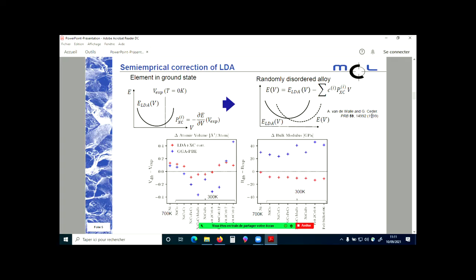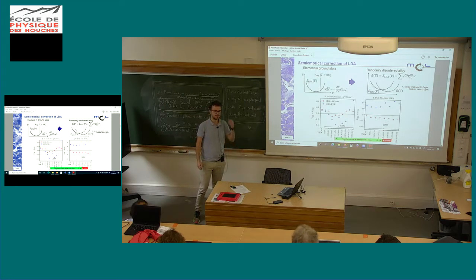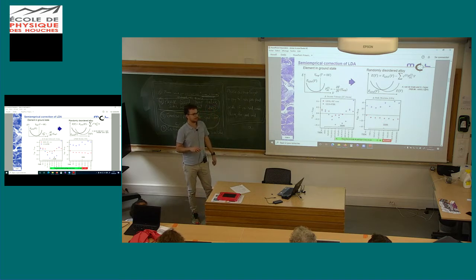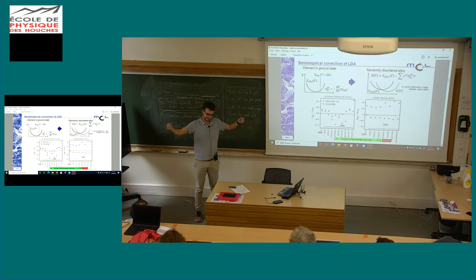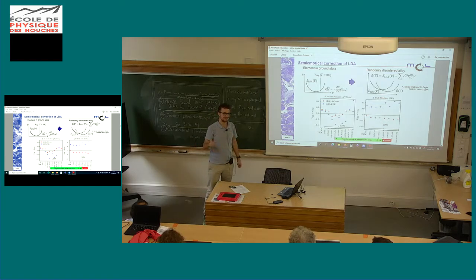Right. So, the point is, as you said, you actually almost need to use LDA to correctly reproduce the magnetic state. But somehow it's an effect that is only taken into account a posteriori. That means you basically just push your result to a place where it then really predicts correct lattice constants. So that's exactly the point of it. You just add a pressure, and you can even argue where these things are coming from. It's really coming from some non-local interactions in the core. So it's not considered self-consistently, and that really helps in this respect.